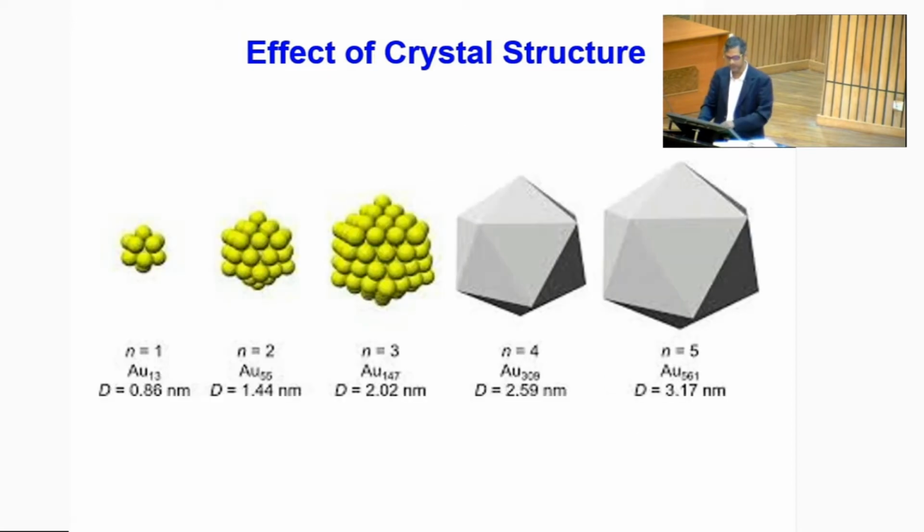So you can now put around the second cluster. If you do that, you need about 55 atoms. So that means in the second layer, we'll have about 40 new atoms, right? That's possible. But you know, FCC crystals don't form cuboid or cubic structures. They actually form what is known as a cuboctahedral structure. It's a 14-faced solid.